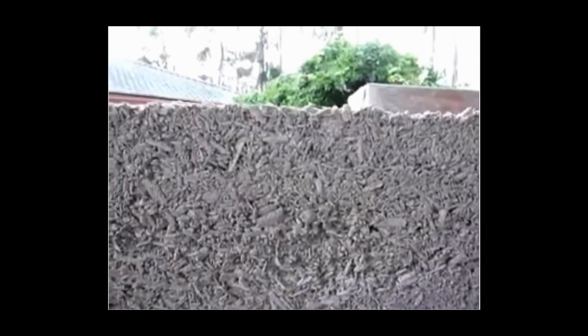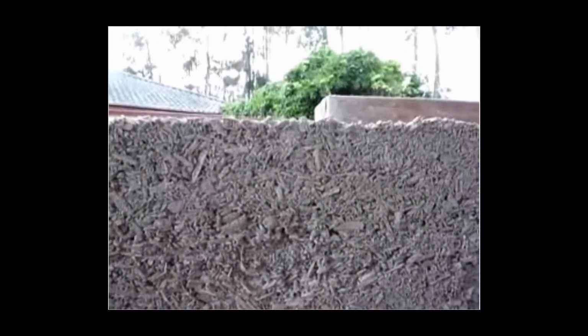After 3 weeks of drying, it looks like the mix we used with only 9 litres of water, with the much drier mix, hasn't bound together properly. And if you touch the wall, large sections can just flake away. This is in substantial difference to the wetter mix, where if you touch it and you rub your hand along it, nothing really comes off the wall. We also did at the top of this wall a slightly wetter mix which used 10 litres of water, and if you brush that, some material comes away, but not nearly as much as the mix we used with only